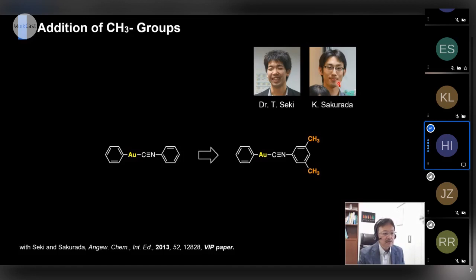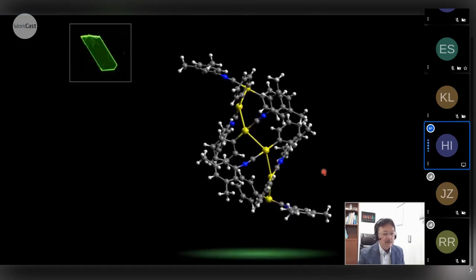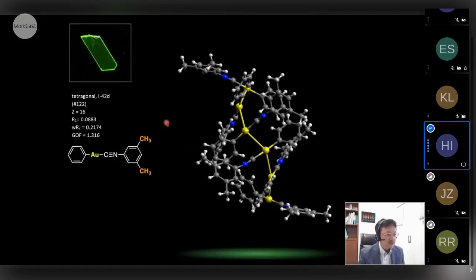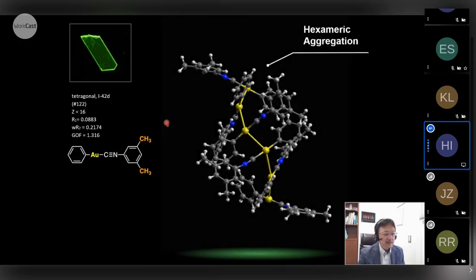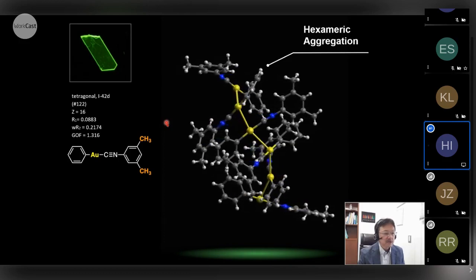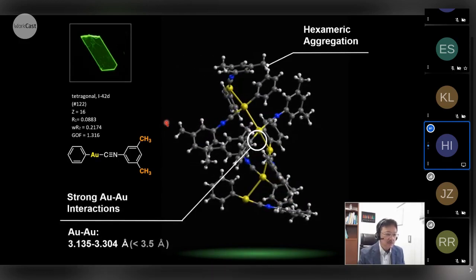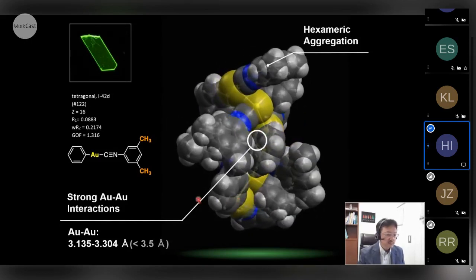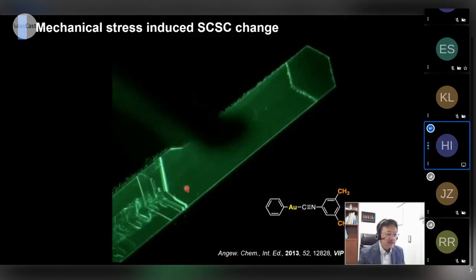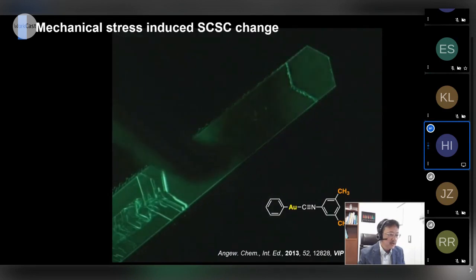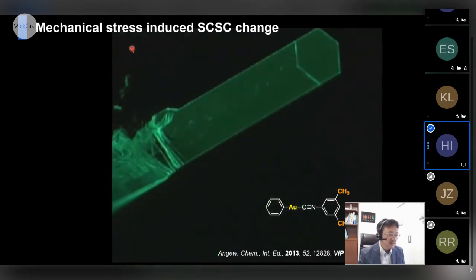And I would like to show another example of single crystal to single crystal transformation, by adding two methyl groups to this phenyl isocyanide complex. This is the crystal structure just after the synthesis. The molecules are aggregated in a hexameric structure, and this crystal structure already shows very strong aurophilic interactions. This is a microscope image of mechanical stimulation of this compound. This is a single crystal of this complex, and my student put mechanical stress on the surface of this crystal by using a metal rod. This is the spot of the mechanical stimulation.